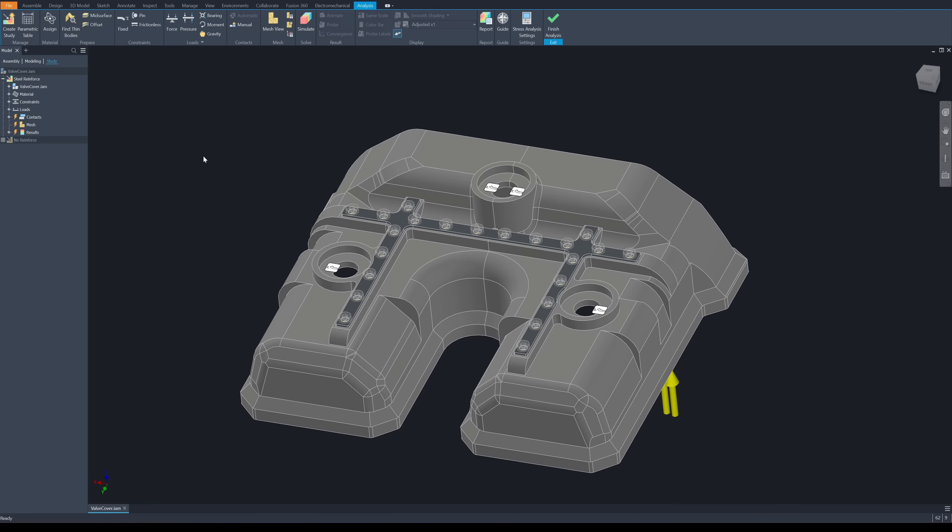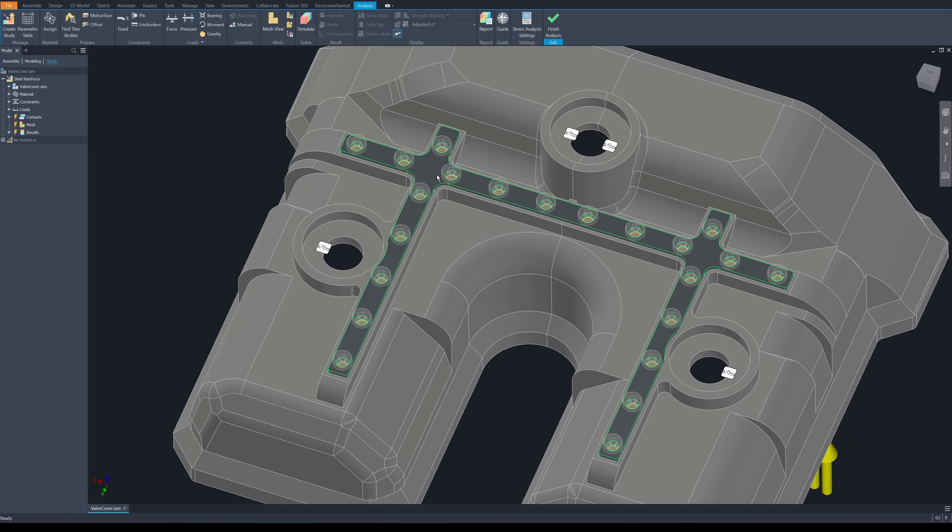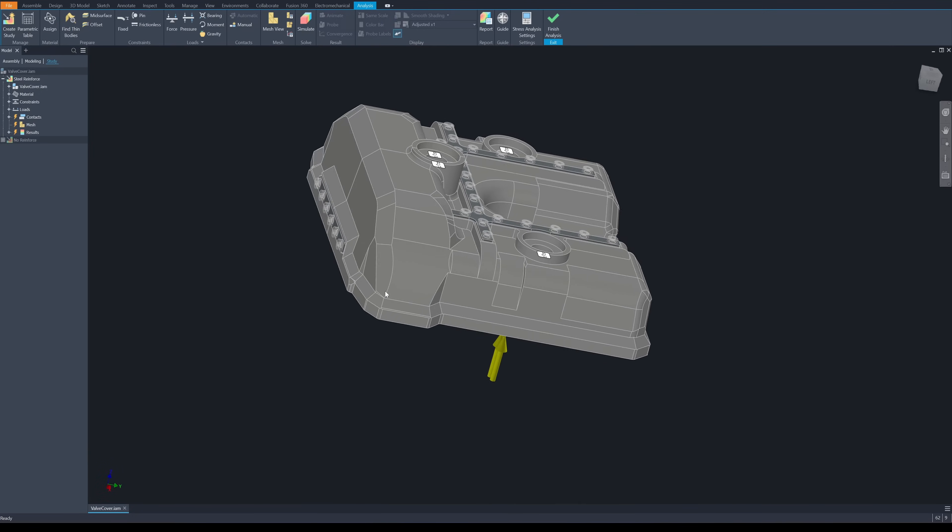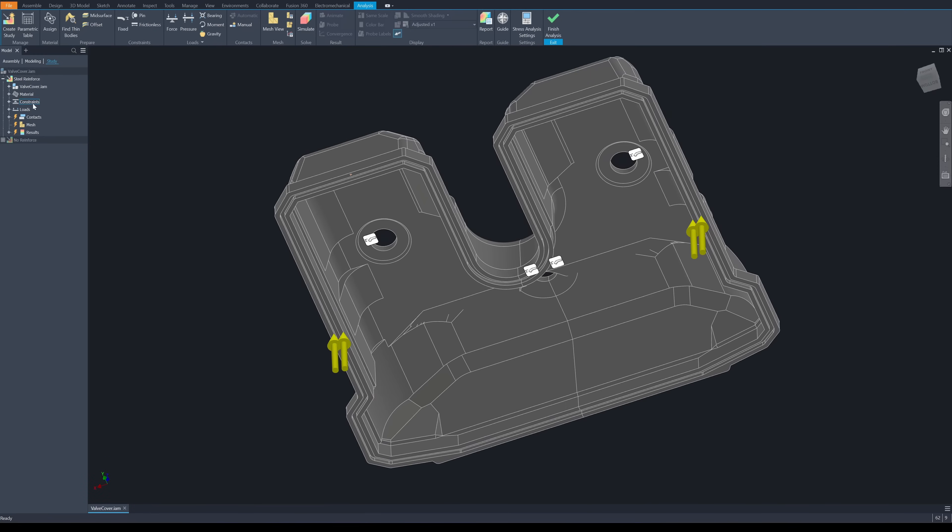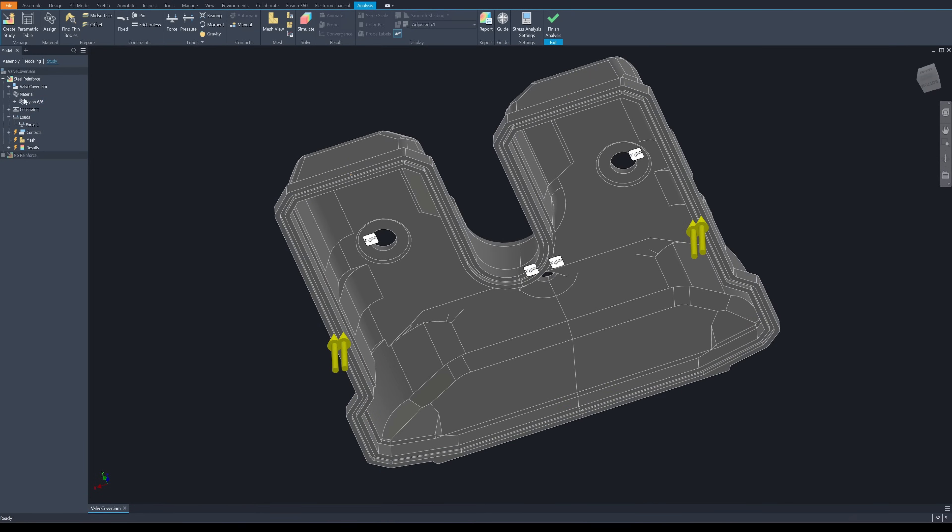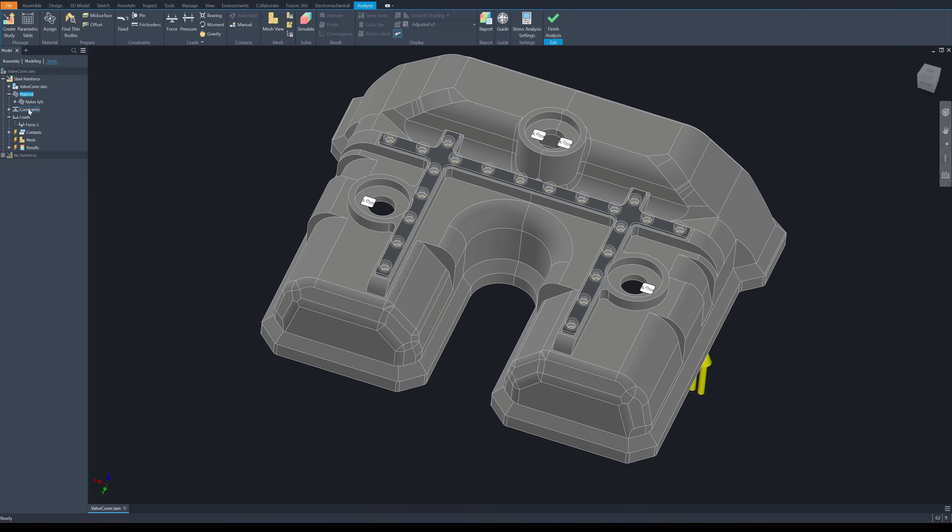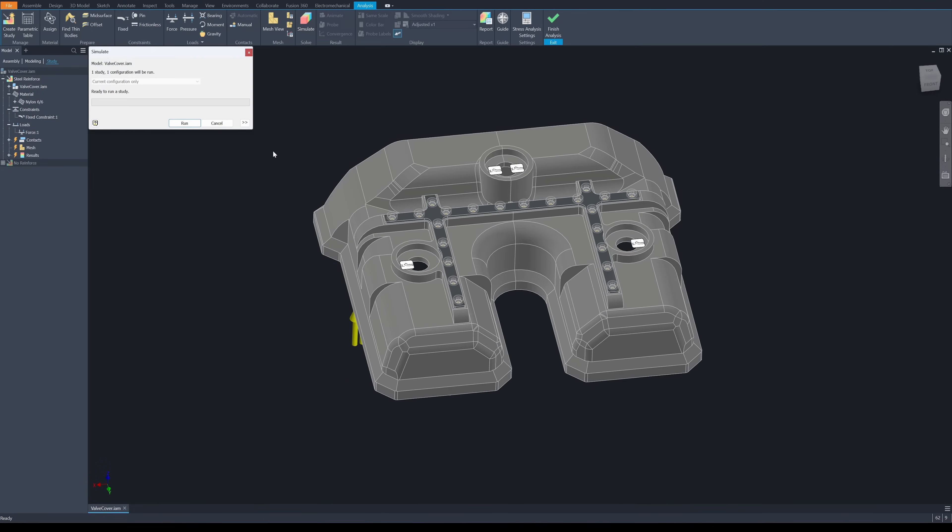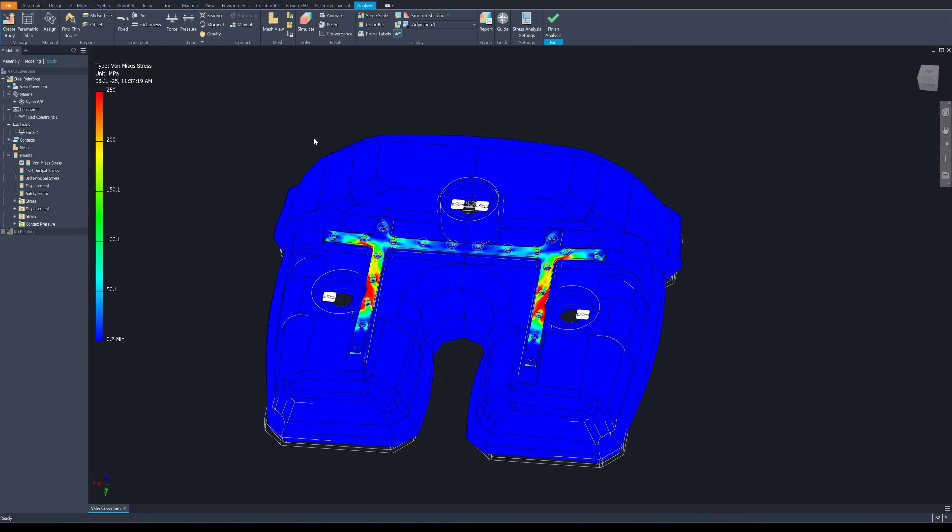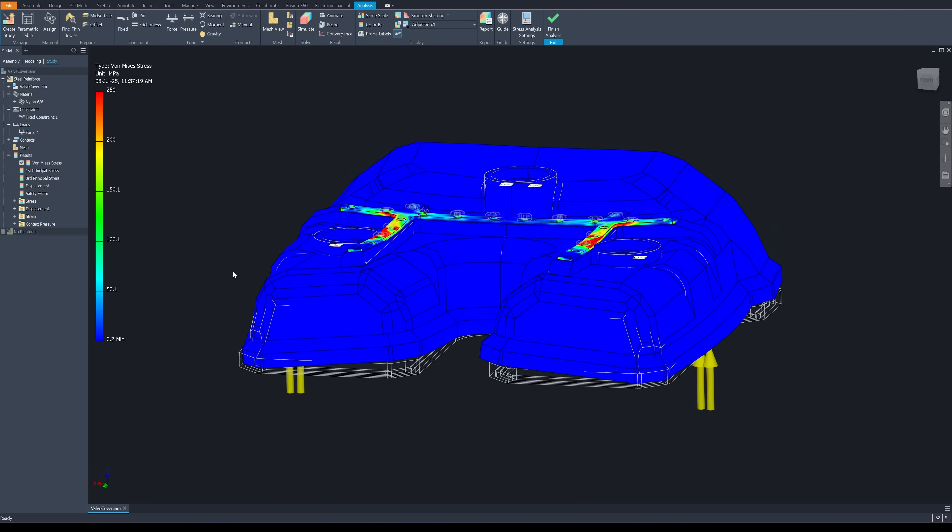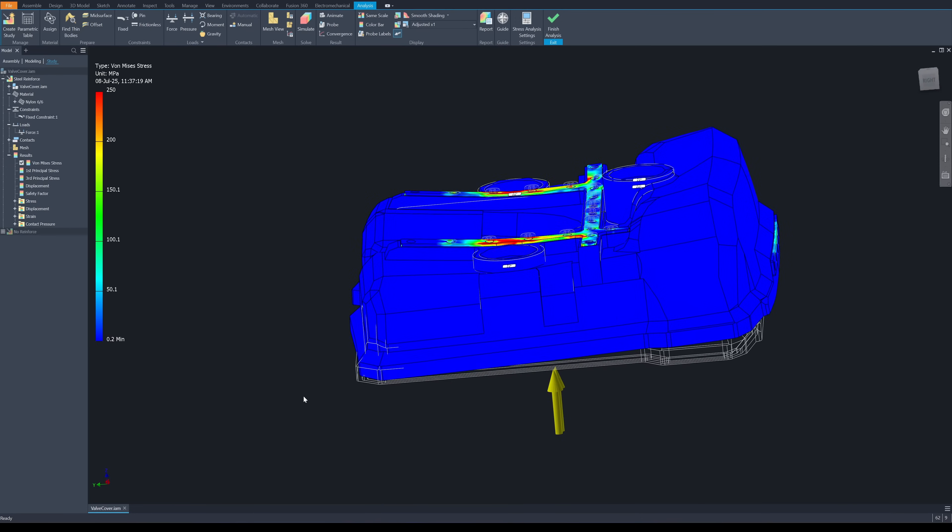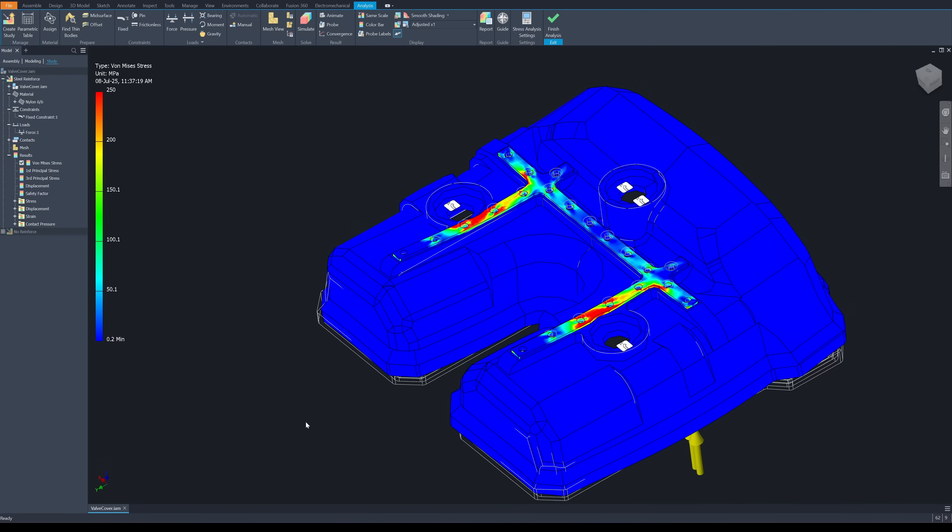Okay, this will be the same model, but I just include this stainless steel strip 2 mm in thickness into the simulation. I apply the same force 2100 and I also apply the same material which is nylon 6 and the same constraint. Let's start the simulation. The steel carries all the load because it's stiffer. When force is applied to the composite model, the steel, which is put on the extreme surface of the object, will carry all the load until it starts to deform, then the load will be applied to the nylon materials.